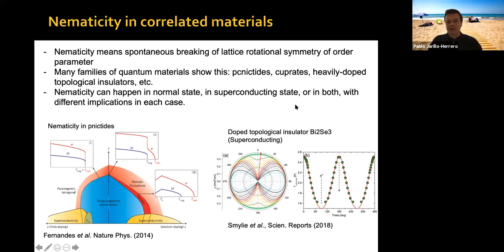More recently, perhaps, doped topological insulators, which are also superconductors, have been shown to exhibit nematicity. Okay, and in this case, for example, you can see that TC varies as you apply magnetic field parallel to the planes of the topological insulator. I think this is for either copper doped or strontium doped bismuth selenide. You can see that TC oscillates, okay? It has two peaks here between 0 and 360 degrees. It has two peaks, which means the system chooses a direction or a director, as Rafael mentioned, okay?